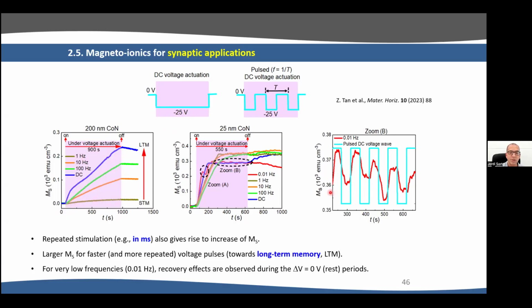And why is that? Because each time we induce something, then when we stop the voltage at 0 volt, in this period of 0 volt, whatever we induce, it relaxes. And we induce again, it relaxes back. Induce, relaxes back. So the net effect is very small. But if we go fast, we induce the Magneto-Ionics faster, and then during this very little time, there's no time for relaxation. So actually, there's a cumulative effect here at 100 Hertz, and we can move from short-term memory, where here we induce just for, let's say, 1 Hertz, so basically 1 second, to long-term memory, where here the memory is permanent.